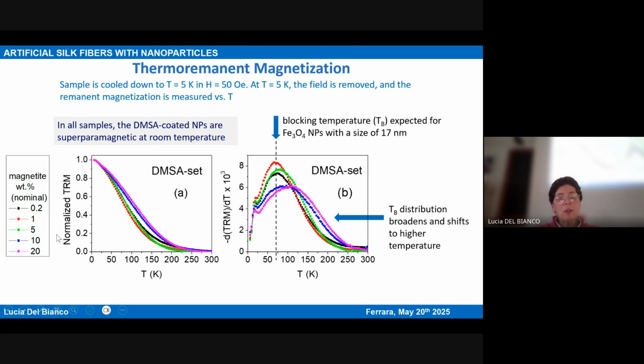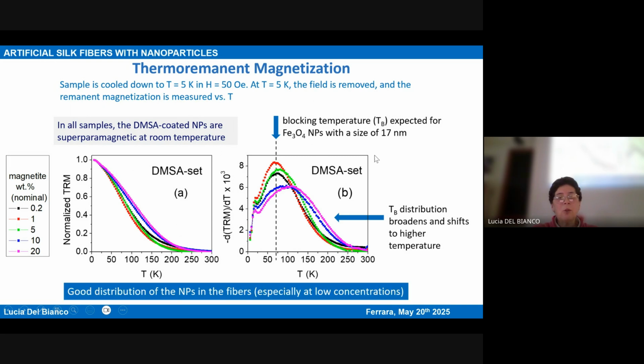With increasing concentration, you observe that the distribution broadens and the maximum shifts a little bit to higher temperature. And this is what happens when the nanoparticles of an assembly start to interact by dipolar interaction. Dipole-dipole interaction. Anyway, the shift is small, and therefore these are good results. Actually, we obtain a good distribution of the nanoparticles in the fiber, which is not at all to be taken for granted. Especially at low concentration, the nanoparticles are very well homogeneously distributed.